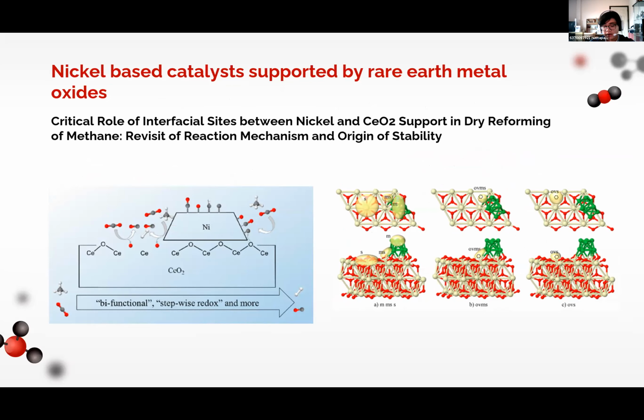And then the use of nickel-based catalyst supported by rare earth metal oxide. This paper explains that the interfacial oxygen of cerium oxide promotes the regeneration of the active site and accelerates the carbon removal, leading to good stability of the catalyst because cerium can be reversibly converted between cerium trication and cerium tetracation in the reaction. During the dry reforming of methane reaction, cerium tetracation will be reduced to cerium trication and oxygen vacancy will be generated. This improves the mobility of lattice oxygen to remove coke.